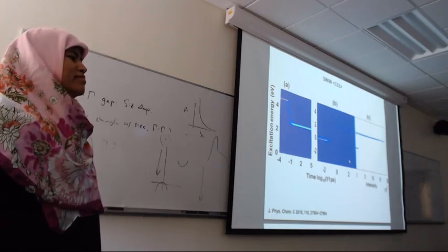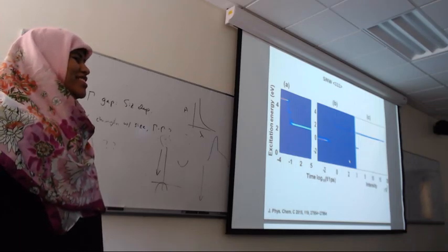Does it make sense to you? Yes. This is not what we were talking about in our most recent ACS Nano paper. It's something different. What we were talking about kicks in at the indirect gap and involves fine structure at the X point. Right? This is different. Gamma-gamma with gamma-X with two channels will have different size dependence.